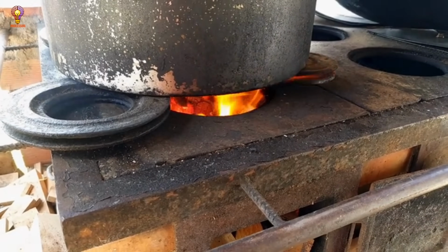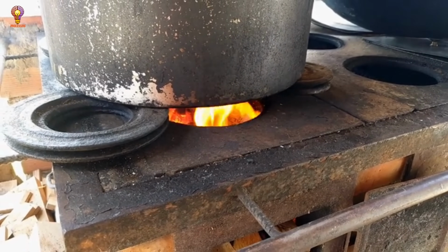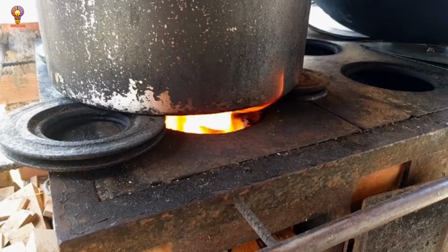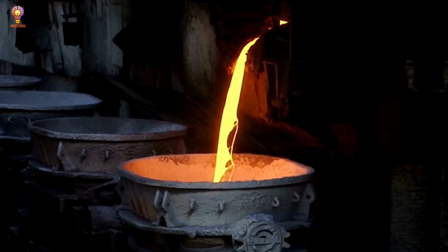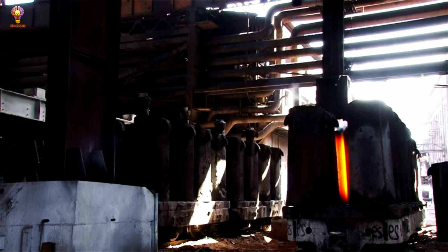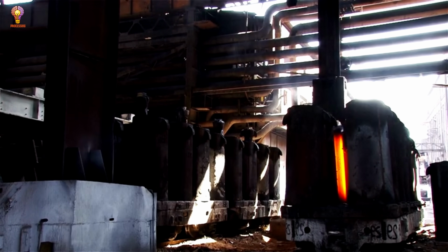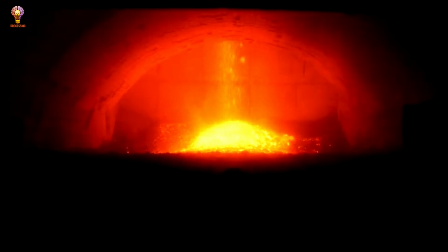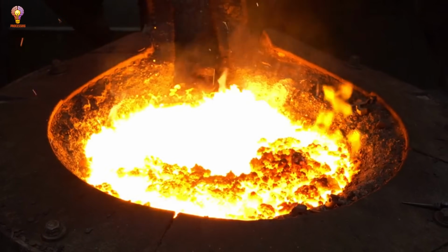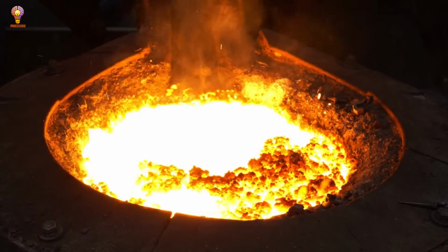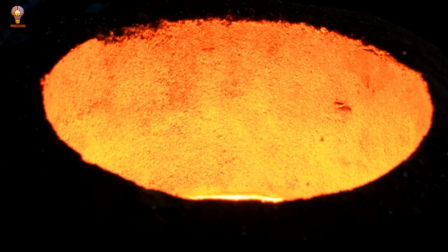4. Smelting. After flotation, the concentrate still contains a mix of copper, iron, sulfur, and other elements. The next step is smelting, where the concentrate is heated to high temperatures to separate the copper from impurities. Blast furnaces or flash smelting furnaces are commonly used for this. In a flash smelting furnace, concentrate is heated rapidly, and sulfur is burned off as sulfur dioxide gas. This leaves a molten mixture containing copper, iron, and sulfur. The process produces copper matte, which typically contains about 60 to 70% copper and a mix of iron and sulfur.